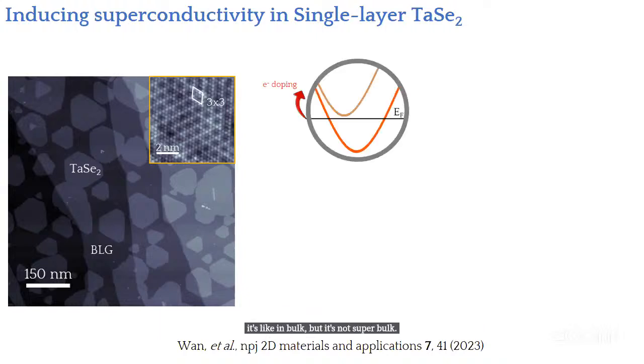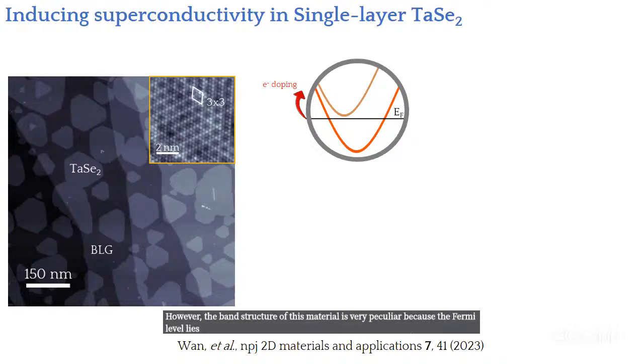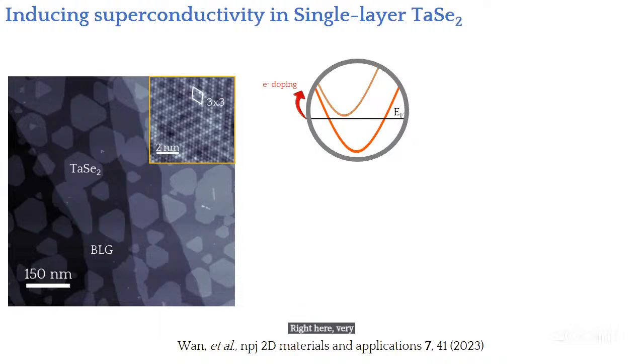However, the band structure of this material is very peculiar because the Fermi level lies right here, very close. By the way, these are the two bands I told you before around the K valley. So these are two spin polarized bands. There is one crossing the Fermi level, but it's not enough to trigger superconductivity. But the Fermi level is super close to the other one. So we thought, okay, let's put a little bit of tungsten atoms and lift the Fermi level here.